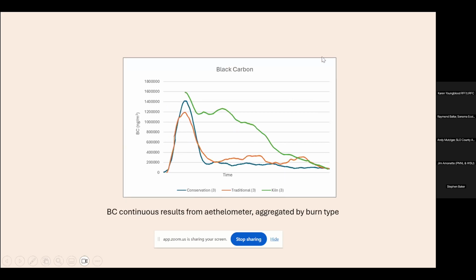Black carbon from the aethalometer. Again, black carbon usually is associated with a flaming or a more high efficiency kind of burn. For the kiln, I think that was maybe just one fire versus a number of fires aggregated for the other two. So it's maybe not the best representation of the comparison between the three types. But again, you'd expect black carbon to be a little higher for the kiln, which was burning at a little higher efficiency level.